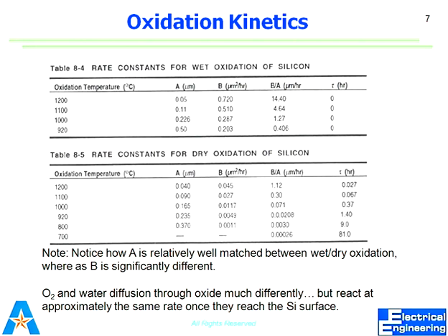So if we have a thick layer, oxygen molecules cannot diffuse through, because in case of a thick oxide layer, it's always a diffusion controlled process. Diffusion is the problem in case of a thick oxide layer. So water molecules have different diffusion as compared to oxygen molecules. That's why water molecules can diffuse easily, and the solid solubility of water molecules is also high. So that's actually the problem with the diffusion. That's why wet oxidation is better in terms of growth rate as compared to dry oxidation.